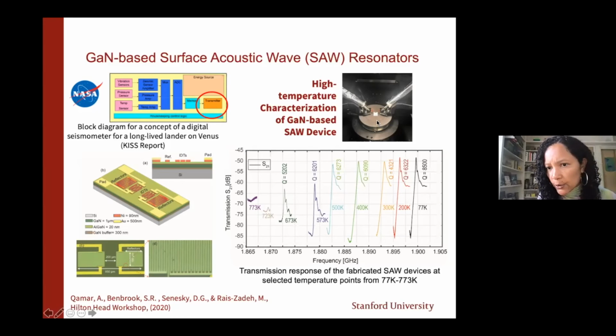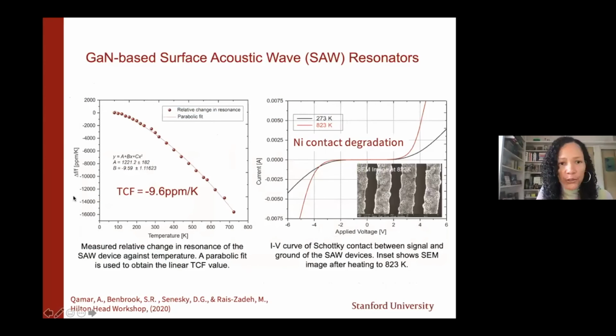So this is our high temperature probe station. We use these tungsten RF probes. At increased temperatures, we can see a degradation or just a shift in the center frequency of these surface acoustic wave resonators. Then we also see a degradation in the Q factor as well. So there's some energy loss, but nonetheless, these guys work in air at such elevated temperatures. Something we measure at various temperatures for resonators is the temperature coefficient of frequency, how that frequency can drop, or for some materials increase, with temperature.